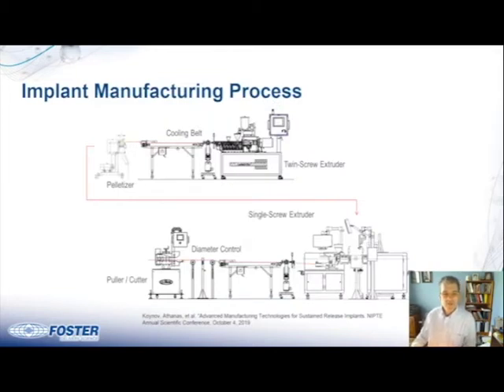So now I'm going to talk about the implant manufacturing process, and a typical implant that requires very precise dimensional control. The material is first compounded or melt blended in a twin screw extruder and then pelletized. And then those pellets are presented to the single screw extruder where the implant is shaped and formed. And it goes through a cooling process. For diameter control, there is that laser micrometer that I talked about, and then a pull cutter. You can produce an implant directly off of the twin screw, but it would require a melt pump. And next I'm going to describe the difference between these two processes, and that'll help explain why.